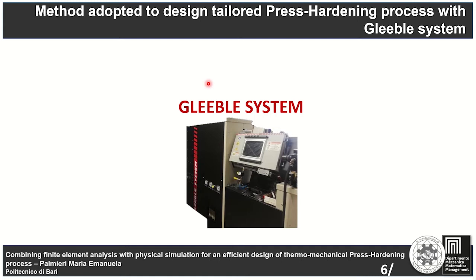However, to carry out this test on the Gleeble system, a careful design of the specimen was performed. In fact, to remain in the austenitic field, it is necessary to respect cooling rates of about 27 Kelvin per second. To respect this cooling rate without using an external cooling system, we reduced the central section of the specimen to dissipate heat more quickly. This study was carried out with COMSOL Multiphysics finite element software.